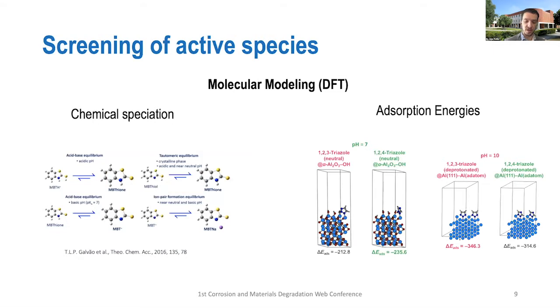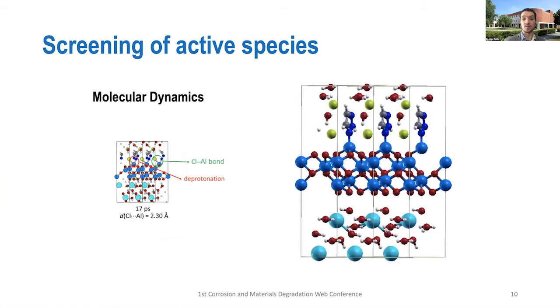Another possibility in terms of screening, of course, is using DFT, which has been used, I would say, widely by some groups, not only to calculate adsorption energy and understand the interaction of the molecules with the hydroxides or the oxide, hydroxylated oxide, or the bare metal as a function of the pH, but also to have insights on the speciation of the inhibitor that we are talking about in terms of acid-base equilibria and tautomeric equilibrium as well.